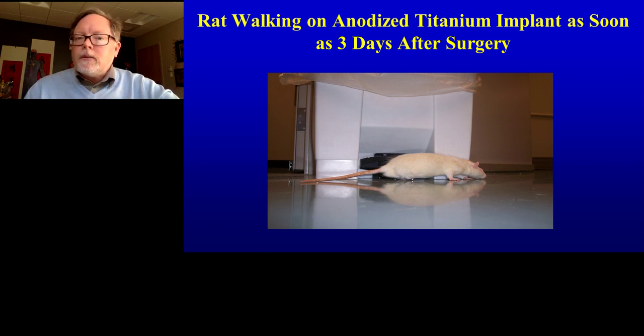So the results from this study were incredibly promising. I don't have a movie here to show you, but I do have the rat. Qualitatively, you can see where the screw is in the back right leg of this rat. And what we saw was the rat was walking on the anodized, the nano-textured titanium implant 3 days after surgery. For the control pin, the one that's used today, this rat did not walk on it for 28 days. And that's as far as we took this study, 28 days. So clearly, the rat felt more comfortable with this anodized implant than the unanodized or nano-smooth implant.